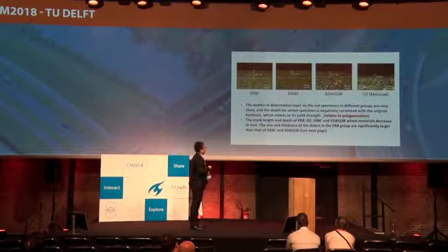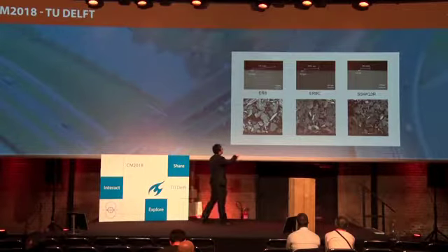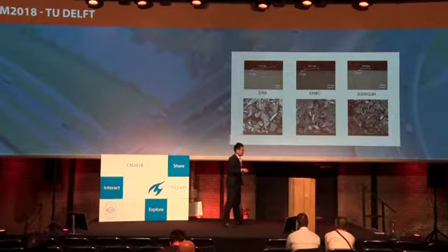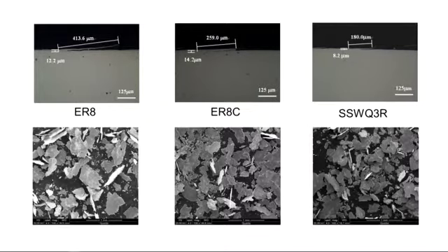And besides, we collected the debris of the different wheel specimens as shown in the picture down the page. We can see that the harder the wheel specimen is, the smaller the debris it finally generates tends to be. And this also explains why the hard wheels tend to have smaller cracks and minor wear volume.